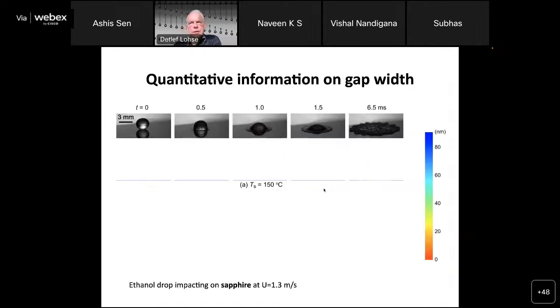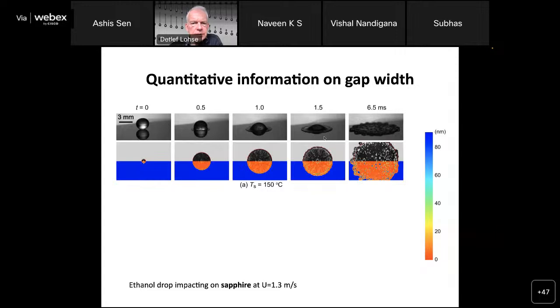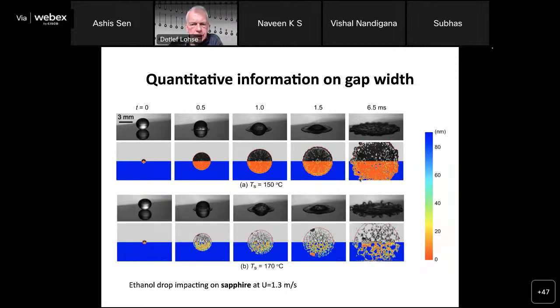The nice thing about TIR is that we can extract quantitative information here. So it's the side view and the bottom view at 150 degrees. And the color code gives the distance in nanometers. So you see red means contact, so 0 here, and blue means very far away. So this is at 150 degrees, simply contact. You see some bubbles right here, but that's about it.